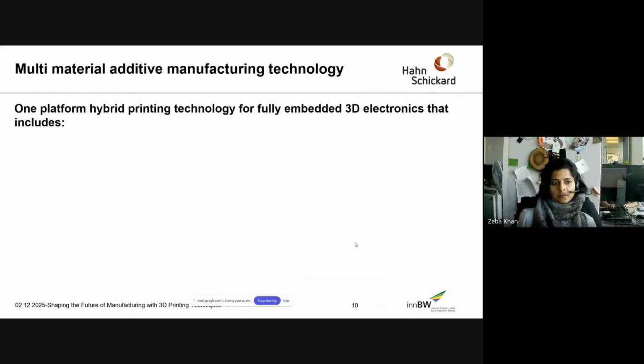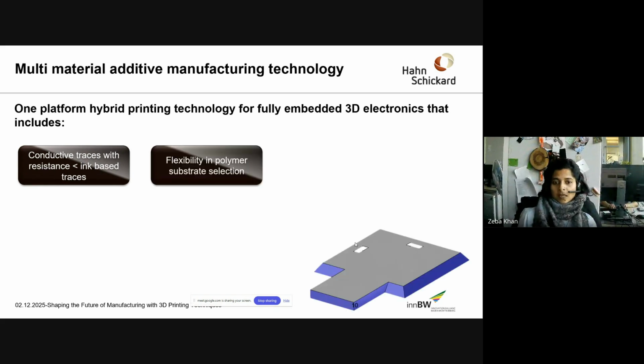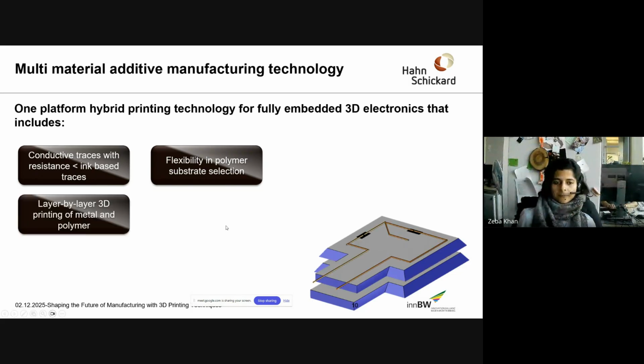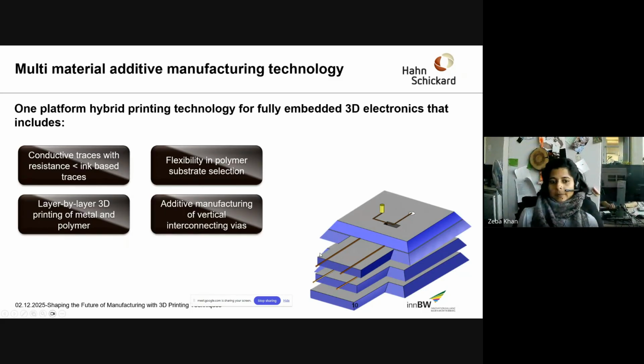And for this purpose, we developed a one platform hybrid printing technology to create fully embedded 3D electronics. This includes conductive traces with resistance less than the state-of-the-art nanoparticle-based ink traces, flexibility and polymer substrate selection, as you see on the right bottom here, layer by layer 3D printing of metal and polymer. So we are able to print substrates, we are able to print conductive tracks shown in yellow here. We're able to also print additive manufacturing of vertical interconnecting vias.